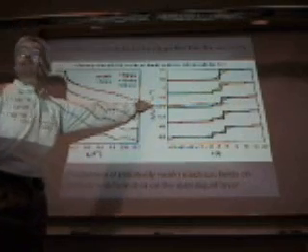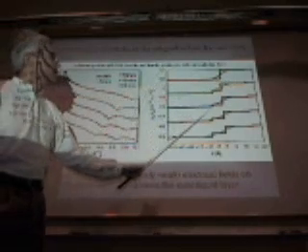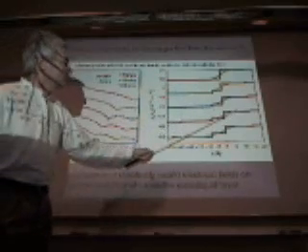Now, when you look at the reconstruction of the density profile, you see that this looks different. You can fit this only with a 2-layer model, where you have one layer which is more dense, again the same density which we always find, 1.25, followed by a thicker layer which has a lower density. Or, because there's roughness there, it's more like a gradient-type density profile with a high density layer close to the silicon dioxide again. That would be the same mechanism, by the way, we just pin those fluctuations.